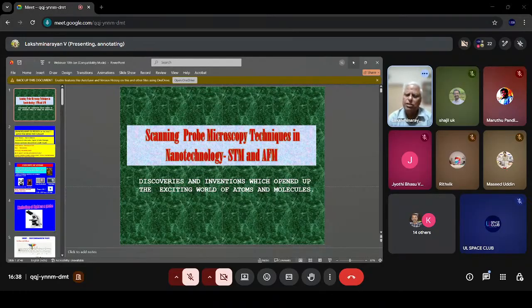Mostly platinum particles. You have platinum, rhodium particles also, and many of these particles are made into nanoparticles, because the platinum loading is one of the major problems in fuel cell research. Where more platinum is being used, it becomes more expensive. So the surface to volume ratio of catalyst is very important. Where the surface area is very high for a small volume, that's a great thing. So that's why nanoparticles. You disperse nanoparticles on a surface like carbon, and you can study with AFM.